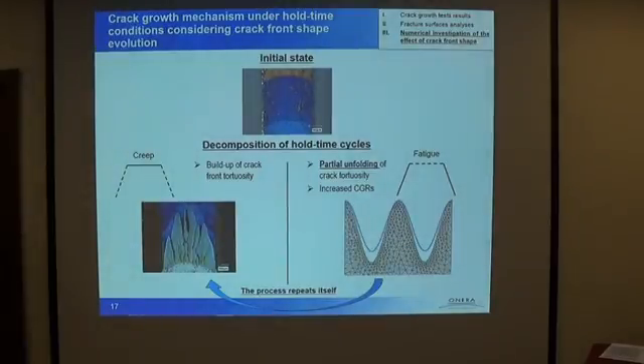Finally, we will assume that crack growth rates under hold time conditions strongly depend on the crack front shapes. To start with, we consider an initial state with a straight through-thickness crack, a very even crack front. And during the creep, we believe that tortuosity will initiate due to local interaction between microstructure, mechanical fields, and maybe environmental effects. And during the load reversal, the fatigue contribution to crack growth, this tortuosity tends to unfold, assuming linear elastic fracture mechanics is still valid in such a case. And so the crack growth mechanism is believed to be a progressive build-up and destruction of crack tortuosity.